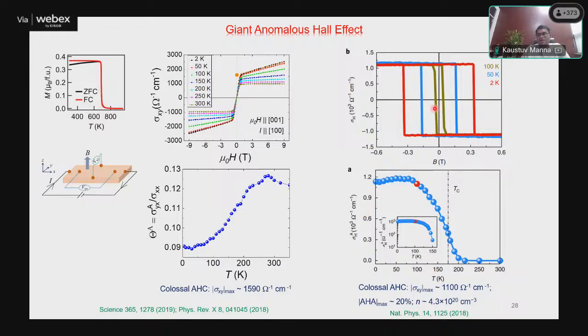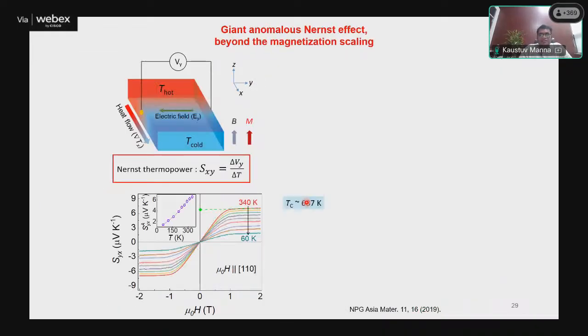The second one is cobalt 3 tin 2 sulfur 2. Here also the transition temperature is high, and the anomalous Hall is also high. But what is important here is that the anomalous Hall angle is very high, 20%. It's huge, 20%, whereas the anomalous Hall angle in this other case is just 13%, as you can see. So this is the discovery of magnetic Weyl semimetals.